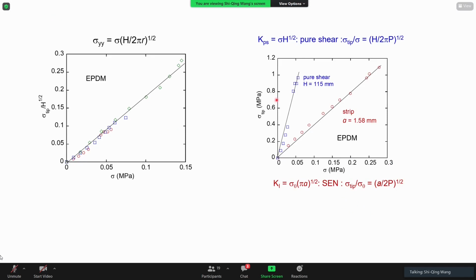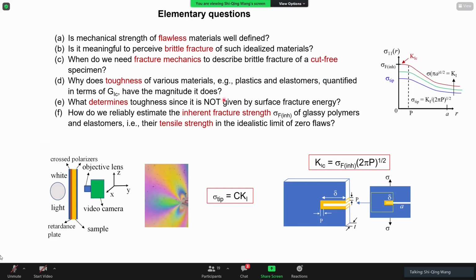The reason we figured out that the prefactor is 1 is that we compared pure shear and the single edge notch. By comparing between them, and at fracture involving the same inherent strength, you could indicate that the prefactor is unique. With that, I think I'm reaching the end of a summary through this birefringence. Looking at the tip, we're not only looking at the tip stress, we're looking at how the stress builds up toward the tip and reaches saturation, as demonstrated here. And this gives meaning about what determines Kc. Of course, that also means we know how Gc is determined. It's related to the strength.